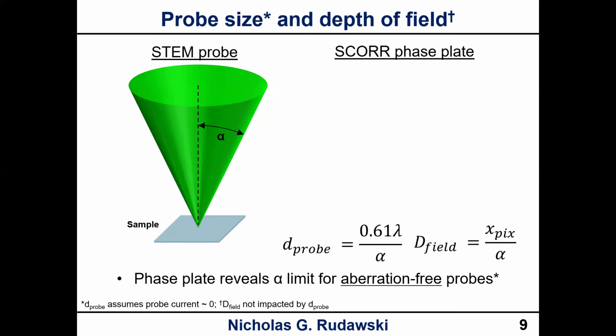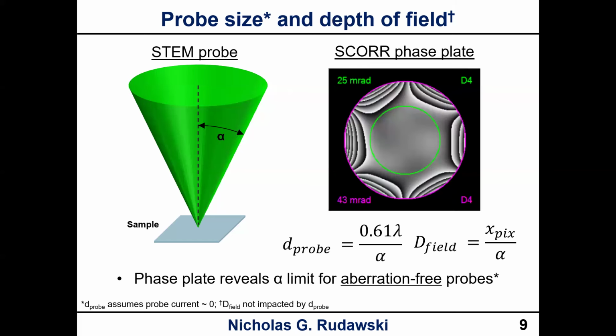So now, again, in order to figure out our limit for alpha, for how big we can make it, we have to look at the phase plate that we get from the tuning, again assuming we have a microscope with Cs correction. In this instance, SCORR is telling us that we can go out to about 25 millirad. So this equation for the probe size is valid up to about 25 millirad. We're also assuming that we don't have any contribution from the current. That's reasonable if your current values are very small, on the order of 10, 20 picoamps or less. Once you start getting into hundreds of picoamps or even nanoamps, this is no longer valid and you have to take that into account.